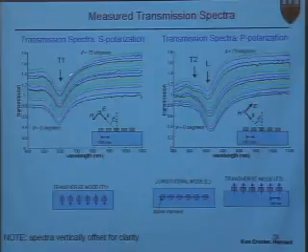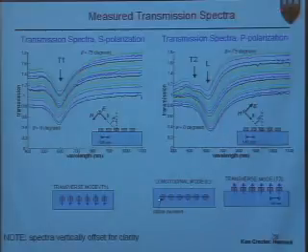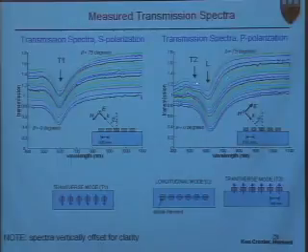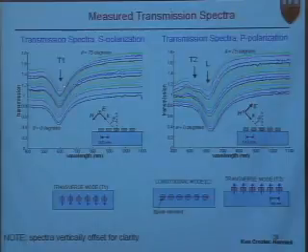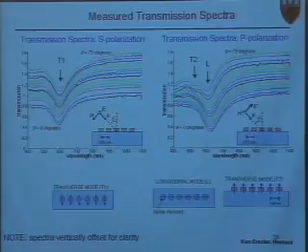And we do this for S polarization, and we do this for P polarization. The S polarization picks up the one transverse mode. The P polarization at normal incidence picks up the longitudinal mode, where all these dipoles are aligned along the chain of the nanoparticles. And at larger angles, it picks up the second transverse mode. And we look at the position of the plasmon resonance in terms of wavelength. We can convert that to plasmon frequency. And by knowing the angle of incidence, we can also find the in-plane k vector, or 2 pi divided by lambda multiplied by sine of that angle.